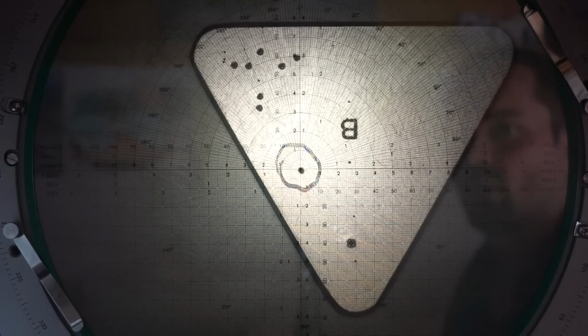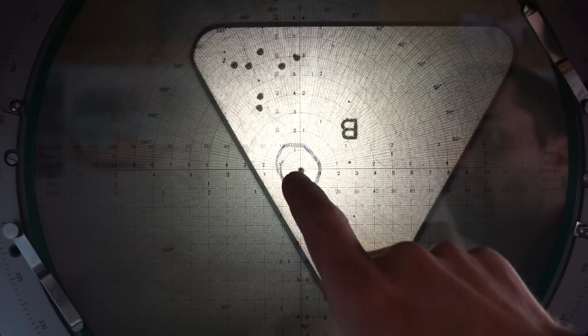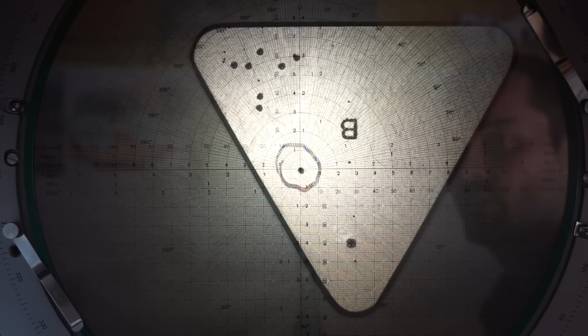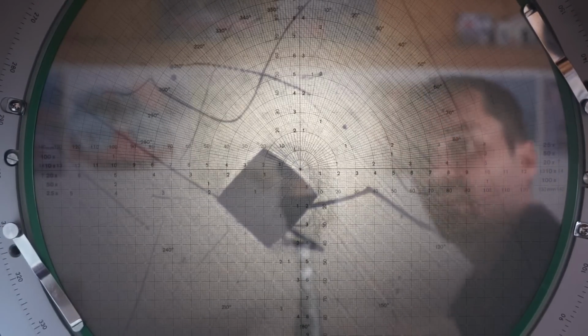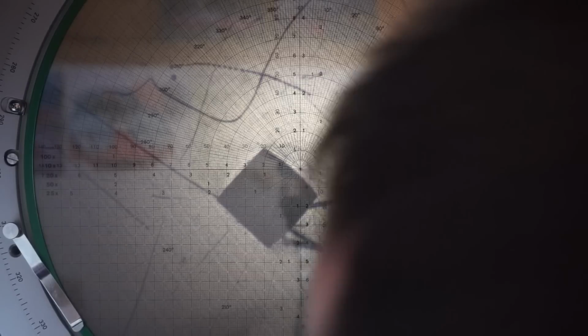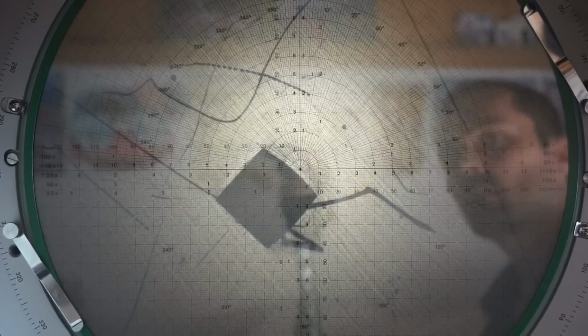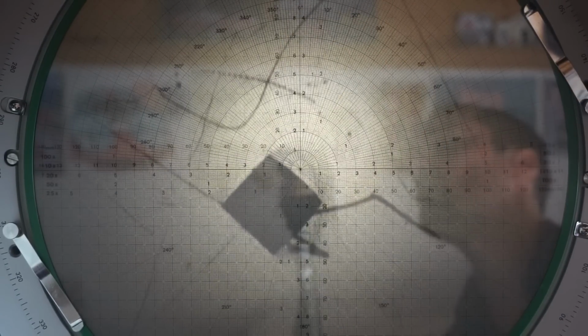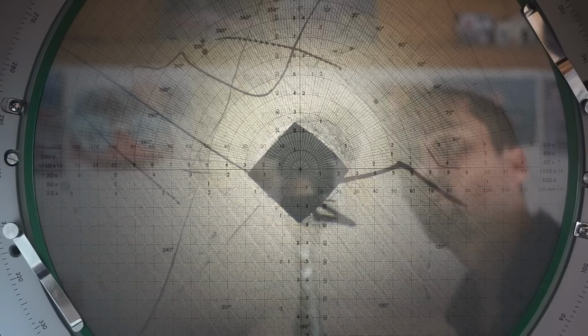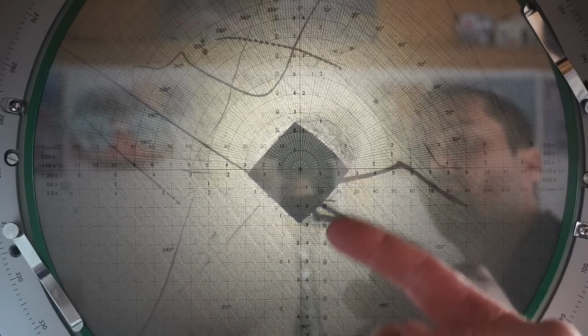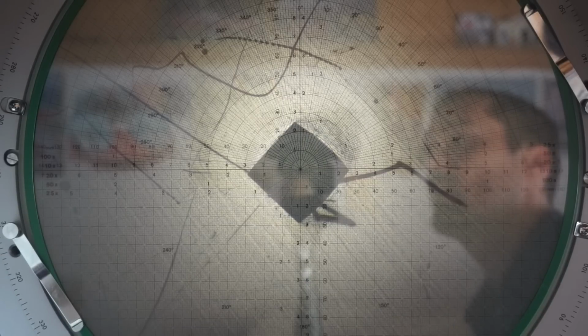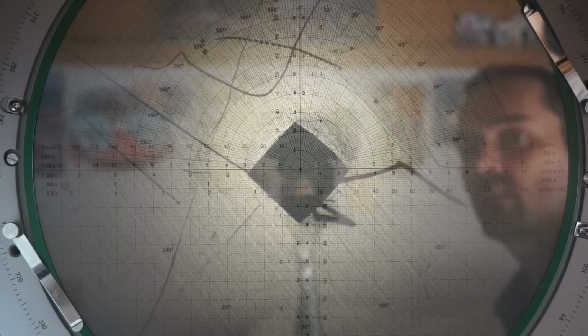Alright guys, so here is the marked indent on the profile projector screen. We're currently at 5 times magnification. So our indent that we want to measure is in the center of the screen, so I'll go to 100 times magnification now, and this should be this particular indent. Yeah, focus is good. Okay, and now you see the indent is a nice square, or almost a square. Here we see some plastic effects that cause the square to deviate from the diamond, but that doesn't matter in the test.